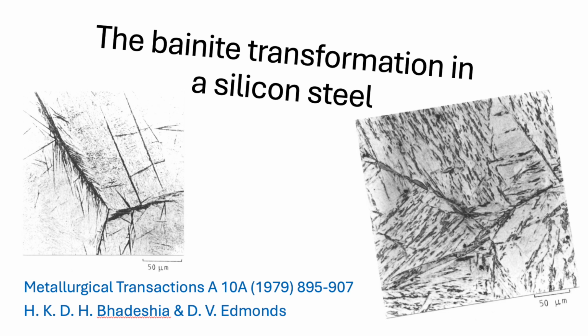And were these carbides cementite in this alloy, even with the silicon? Yes. Surprisingly, they identified cementite even at very short transformation times, like just 2 minutes at 300 degrees C. The silicon didn't fully suppress it at these lower temperatures. Interesting. Did they check for other types of carbides, like epsilon carbide? They looked, but didn't find epsilon carbide. They suggested the high manganese content might have stabilized the cementite phase instead. Okay, so cementite forms early in LB.